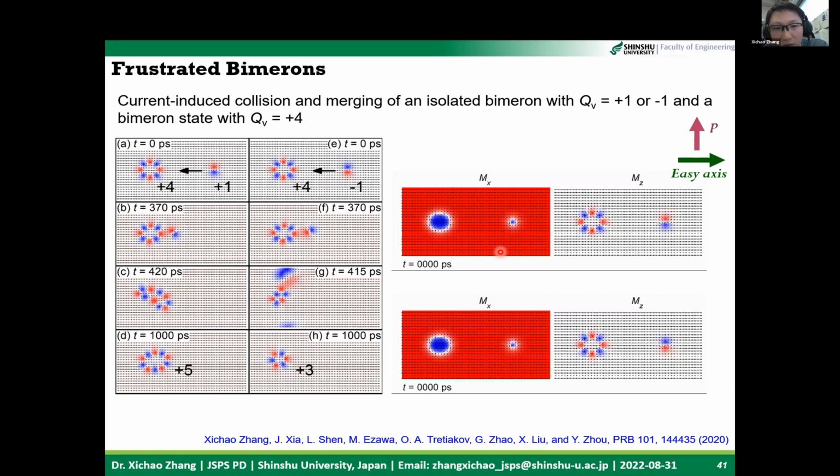That means, for example, if you have skyrmion numbers 1, 2 and 3 in the system, maybe the skyrmion with number 1 is the ground state and the others will be excited states. In such a case, skyrmions with a high skyrmion number may be easily destroyed due to, for example, thermal effects. So sometimes it is difficult to have topological spin textures with a high topological number. But I think there should be some materials where you can stabilize skyrmion textures with a high topological number.